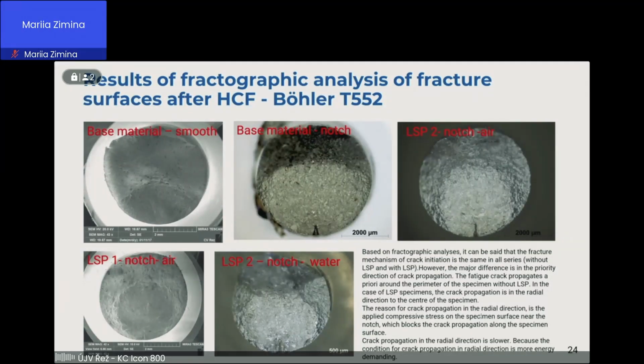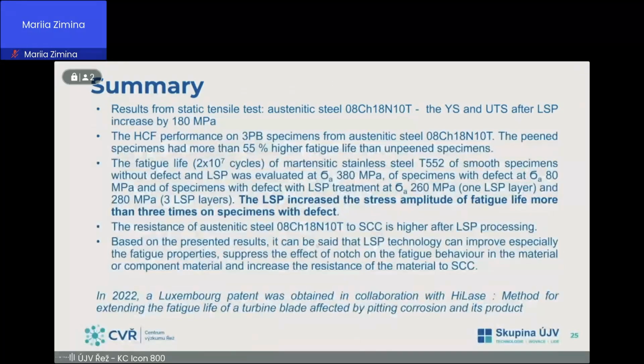The reason for crack propagation in radial direction is the applied compressive stress on the specimen surface near the notch, which blocks the crack propagation along the specimen surface. Crack propagation in radial direction is slower because the condition for crack propagation in radial direction is more energy demanding. Yes?